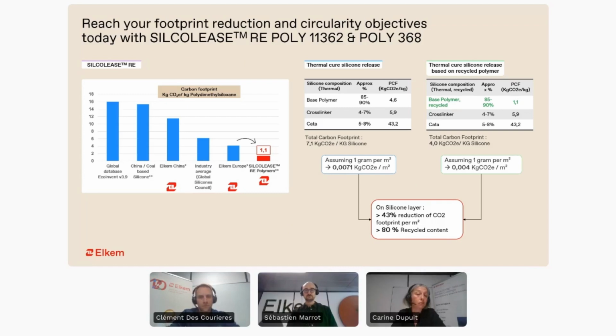Nevertheless, using more than 80% of recycled polymers in the formulation clearly helps you to achieve your sustainability targets, since the total carbon footprint of the system will be reduced by more than 40% per square meter, which is very important. Thanks to these two Elkem recycled products, you will stay ahead of future regulatory change, anticipating future requirements and specifications.